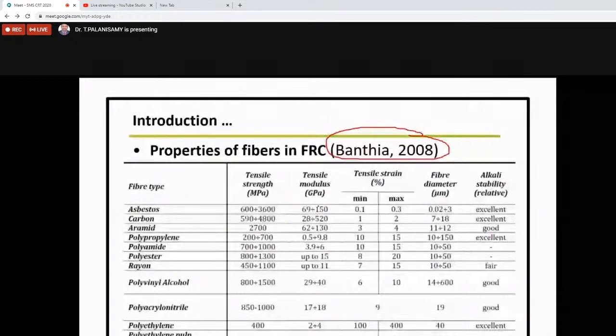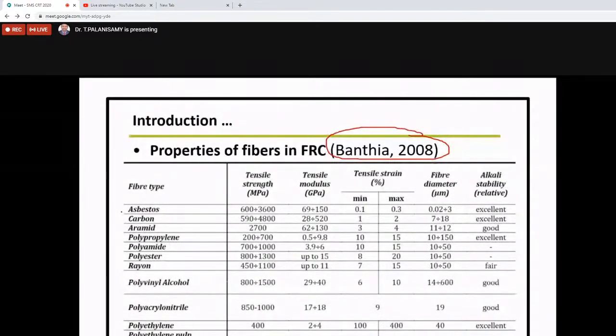We have also come across a number of fibers, such as the asbestos fiber. You can see the asbestos sheet used for roofing. That fiber is called asbestos fiber. The tensile strength is nearly 600 to 3600 MPa. Then carbon fiber, this is a high strength fiber also. Tensile modulus is also high. Even we have 520 high tensile strength carbon fiber. We did some work with carbon fiber for repair and rehabilitation.